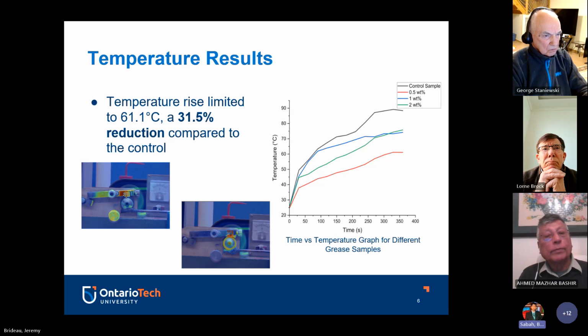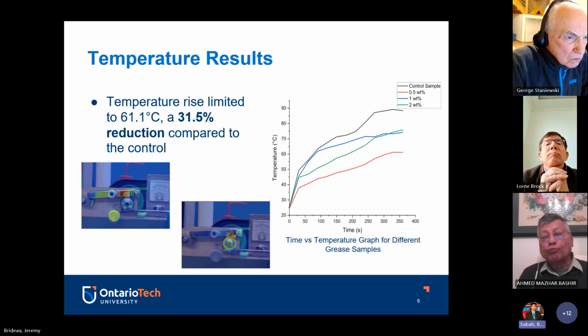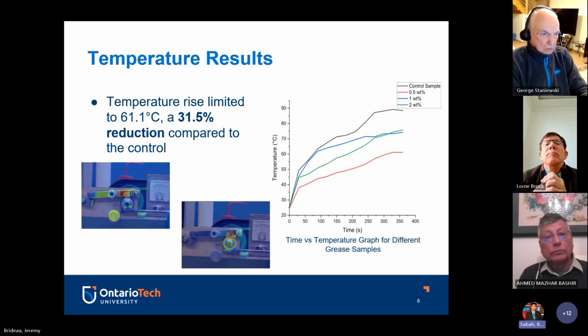Now, we did notice diminishing returns in regards to the 1% and 2% of graphene content, where they performed very similarly in terms of temperature, which meant that we had a clear front runner for the best optimal concentration for graphene inside these different greases. You can see on the bottom left-hand side there, those are actually thermal images that we took of some of the different samples. So you can see the darker area under the 25.1 is actually the grease that we applied. And then you can see how the temperature has increased over time.